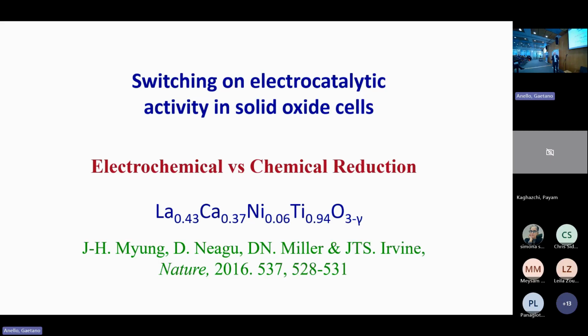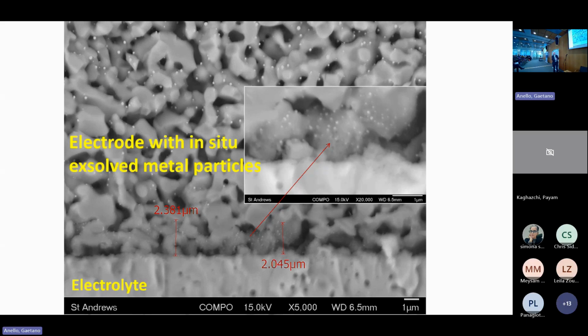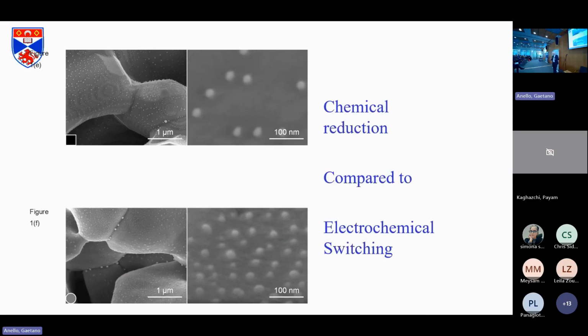And then looking at hydrogen production. There's Jeha and Dragos. This work on lanthanum calcium titanate, doped nickel. We made first time a non-ceramic electrode, so pure perovskite that's been reduced to produce nickel nanoparticles. If you look at the crystal structure, materials processing is very important for what we do. So you need very nice interfaces, good crystals, but you can see very nice nanoparticles by chemical reduction. If you apply 2 volts without reducing it in a non-reducing atmosphere, you get even more nanoparticles. That's what we call electrochemical switching.